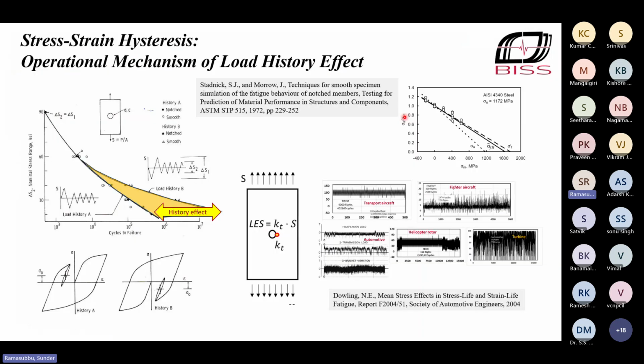So if you have a mean stress effect on a notch, this was established in a very innovative, beautiful experiment performed by JoDean Morrow and his student Stadnick back in the early 1970s, where they applied a prior load to induce residual stresses at the notch root. And then they found that the fatigue life depended greatly on whether they went down first or up first, because that way you're reversing the residual stresses at the notch root. So that is the history effect.